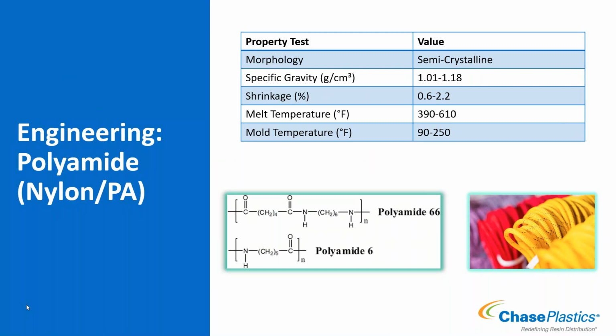Specific gravity ranges from 1.01 in your long chain grades up to 1.18 in your short chain grades, more like a 4,6. And then your shrinkage also has a varying range because we're talking about a bunch of different materials at once, so 0.6 to 2.2 depending on which nylon material type we're talking about.